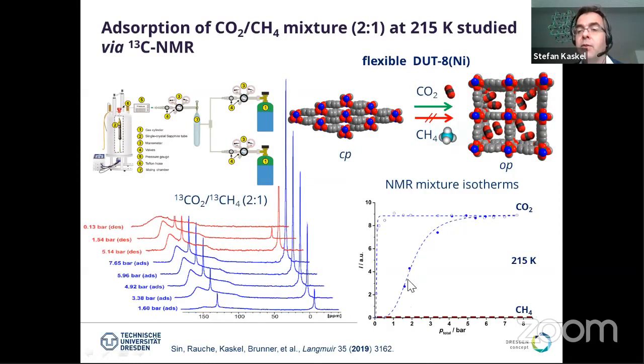And you get a very similar gating behavior in the mixture. And we also know where the adsorbed methane would be located. In this case, you have to believe me that the adsorbed methane would be observed here, very close to the isotropic signal. And we can show that there's no methane adsorbed, at least in the limits of the method, the NMR spectroscopy. The sensitivity is not ultra high, but it is a very good measure.